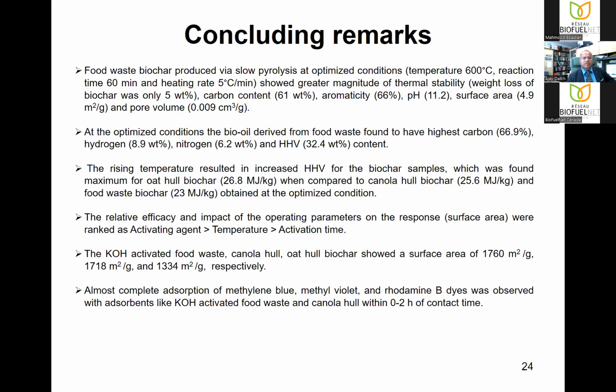And also we found that the oil that is produced from food waste has a highest carbon over 67%, hydrogen over 9%, nitrogen over 6%, and heating value over 32 megajoules per kg. I did not present the results on bio-oil, but just wanted to let you know that we have extensively worked on the bio-oil analysis as well. And this material has a higher heating value, so it is also a good sign.